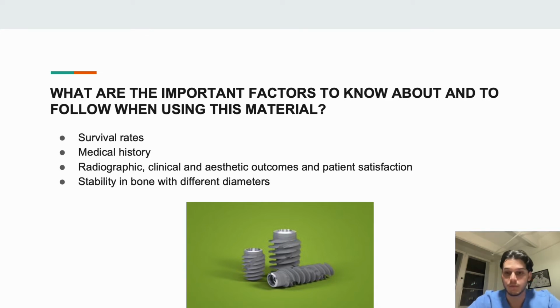Another important factor to follow is the clinical and aesthetic outcome, and of course patient satisfaction. So we have that the patient bone level was between 0.10 and 0.27 millimeters, and the probing pocket depth was 2.57 millimeters, which basically stated that there was no difference between augmented and non-augmented sites. For the ICI test, which is a test done for aesthetic purposes, the results were 67 and 75% of the cases, which is a pretty high number for the ICI test on aesthetics.